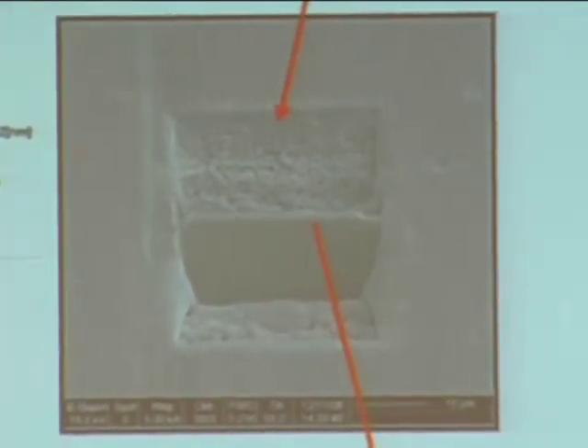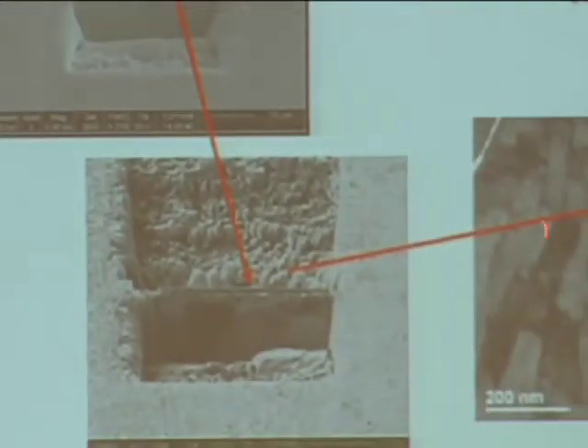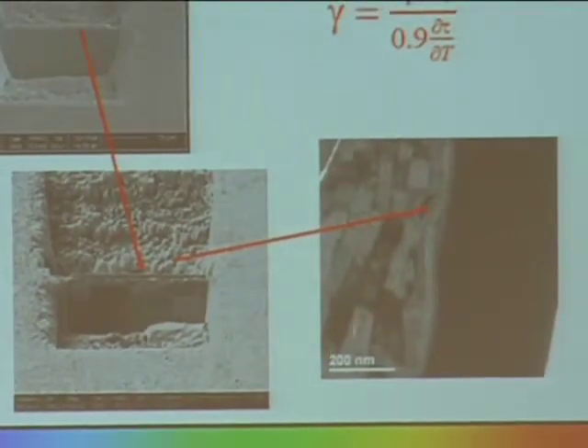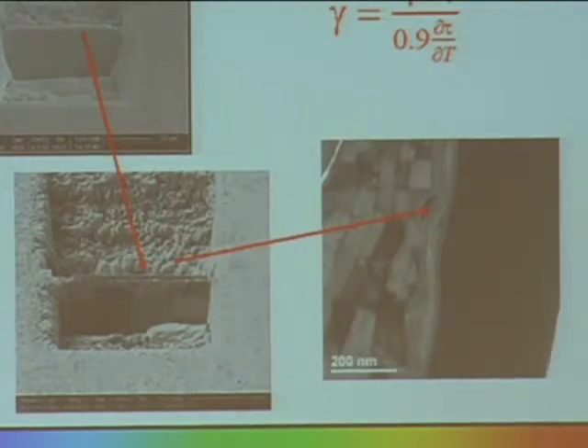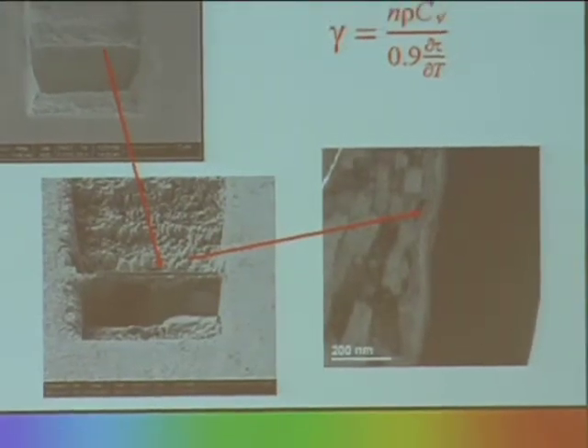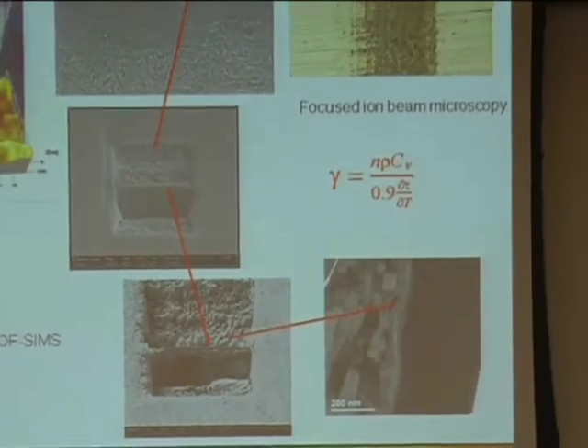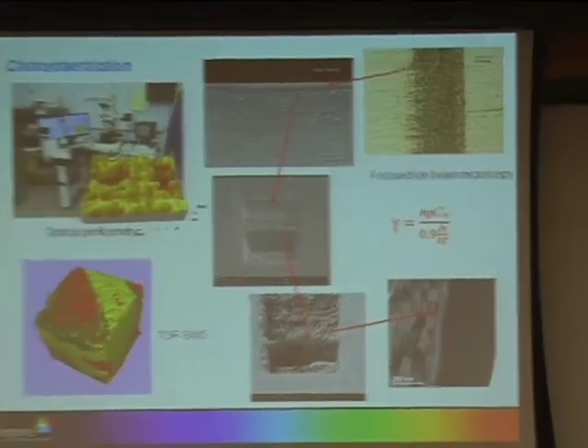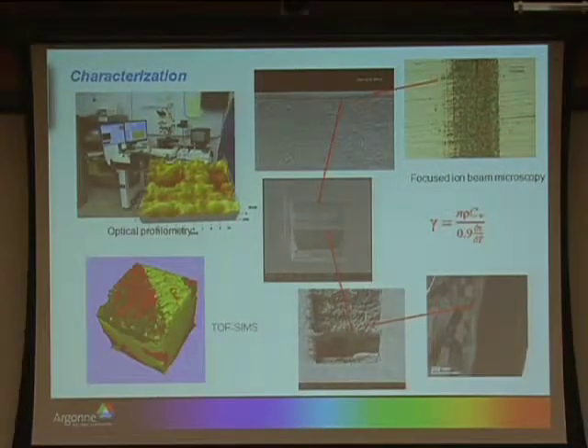This is sufficiently thin that you can then put it inside of a transmission electron microscope and see changes in the microstructure. You can see how you're starting to form an aligned texture in this case. But also you can look at the very near surface region. You can actually identify the formation of this protective film. You can look at its microstructure and so forth. We're also utilizing time of flight secondary ion mass spectroscopy to look at the composition of films. In this case, it's a diamond-like carbon film, looking at the wear track and seeing that it has a different composition than in regions where it has not been worn.